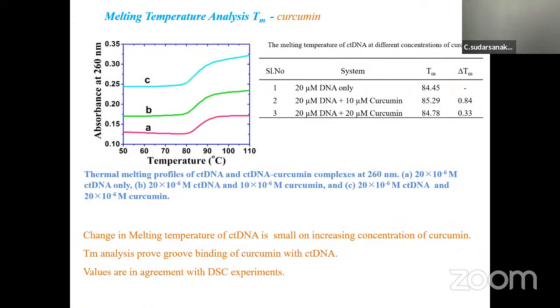Curcumin and piperine are groove binders. Another way of doing it is the melting analysis. If you look at the absorbance of the DNA at some particular concentration of the drug, you measure the absorbance with increase of temperature. At the melting temperature, there should be a very large absorption of energy, especially something like a 7 to 8 degrees Celsius difference for an intercalator. But for a groove binder, it will be something like 1 or 2 degrees. So in this case, you find only very minor changes.